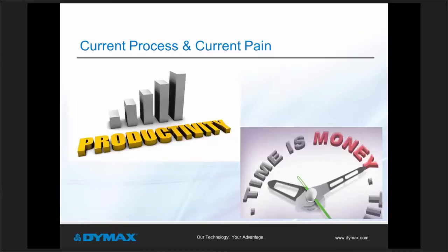As I mentioned earlier, the challenge presented by the customer was to replace the current latex-based masking with a faster curing, more reliable, and easily applied and removed masking that was compatible with the connector pins. This masking had to provide the required protection, and the PCB also had to pass the current SIR testing after removal of the masking, while being compatible with the solvent-based conformal coating. Added to these issues was the requirement to increase production efficiencies to meet the planned 30% demand increase, while working with the same floor space and doing so at a comparable or lower cost.